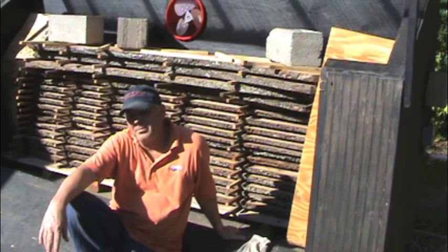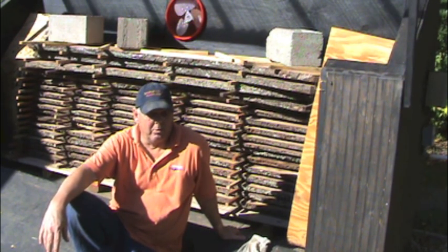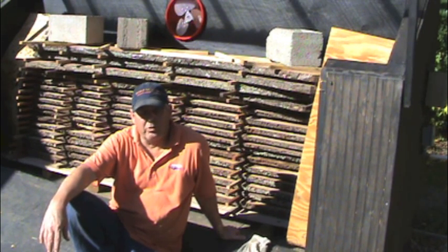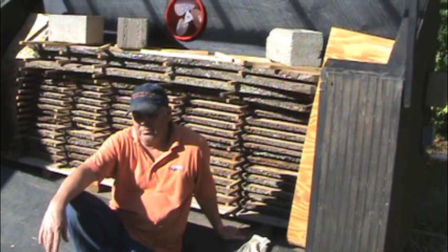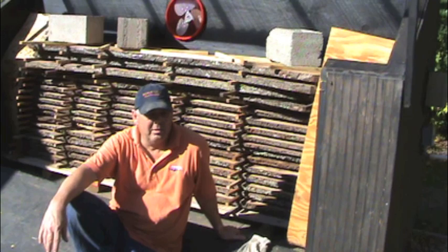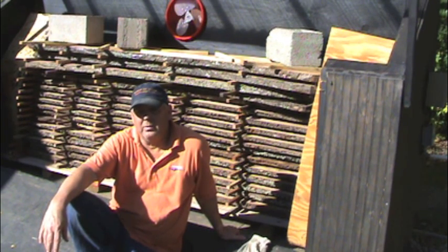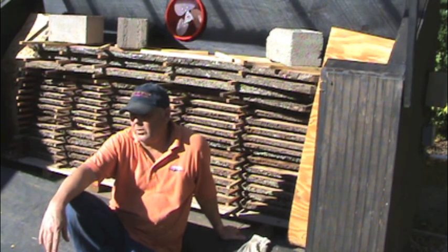What happens if it dries too fast? Well, wood dries from the outside in. In other words, it can look dry on the outside, feel dry. You can check it with a moisture meter, and it will even give a dry, low moisture content reading. But you cut it open, and the core will still be wet. That is a moisture imbalance, and you always have a moisture imbalance when you dry, because like I say, it dries from the outside first.